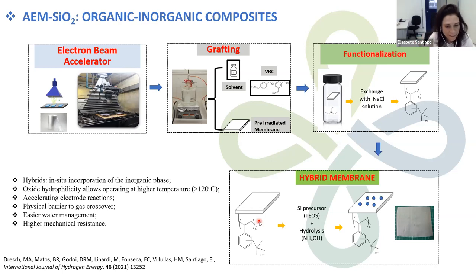So the idea of using silica is due to the oxide hydrophilicity that allows this membrane to be operated at higher temperatures, as high as 100-120 degrees. The increase in temperature is important for electrochemical reactors because it promotes the acceleration of electrode reactions. And moreover, the presence of the silica or an inorganic phase can also act as a physical barrier to gas crossover, very common in solid electrolytes. And it can facilitate water management and promote a higher mechanical resistance.